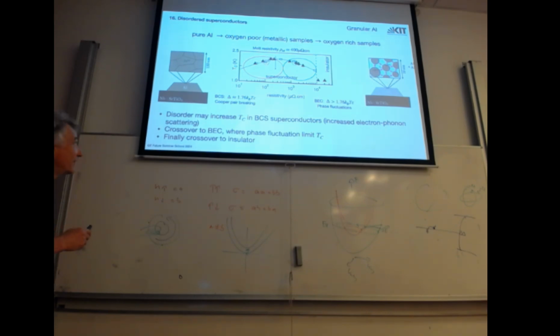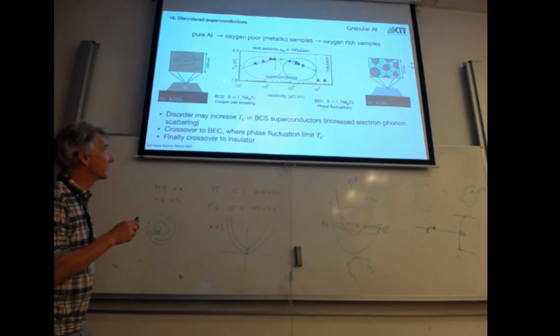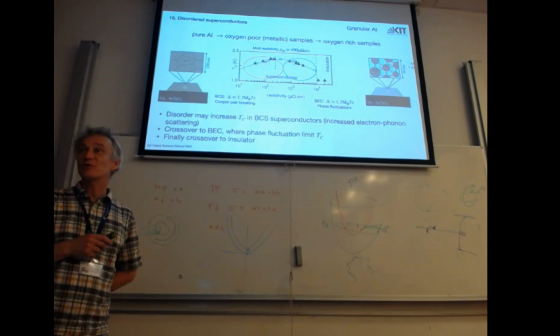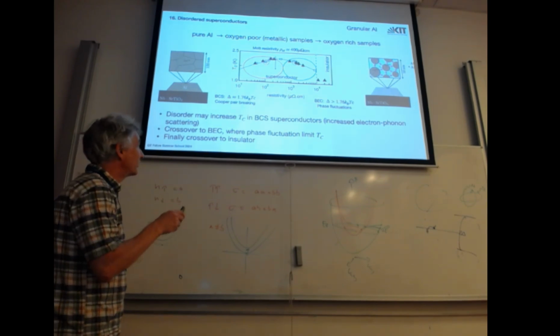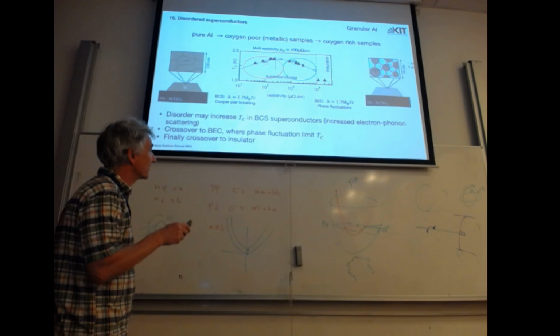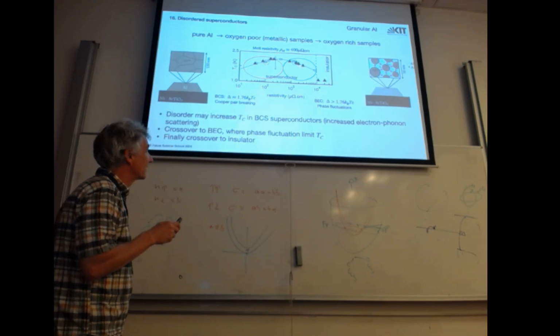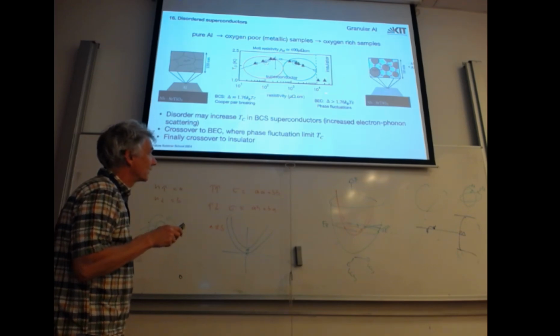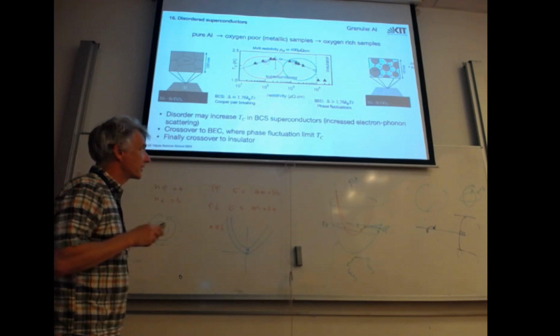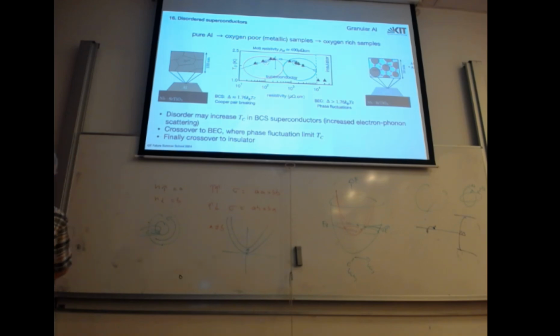I'm not an expert there, but the interesting thing is that on this side, where you have not a lot of oxygen, you follow the relation of the gap and the Tc that is given by BCS theory. So this looks like a conventional superconductor, if you like. And if you go above this point and become more insulating, delta is much larger than 1.76 kTc.